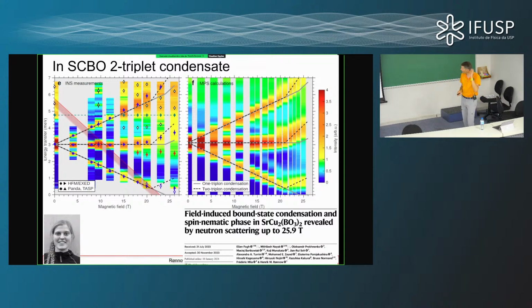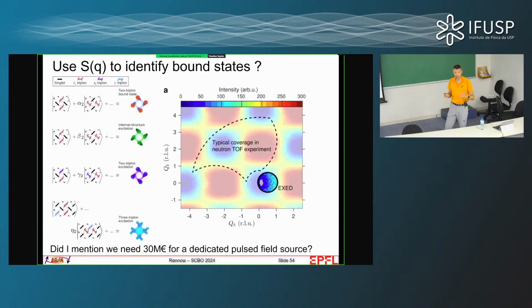Okay? So now I'd love to show, by measuring the intensity of these as a function of momentum, which of these kinds of excitations we have. But unfortunately, in that experiment at 26 Tesla, the range of Q that we could access was this big, and we would have needed to access ranges this big to be able to see the predicted variation. And so at 26 Tesla up in this high state, this will take quite a while. Currently, we do not have any instrument, any magnet going high enough in field to do that.